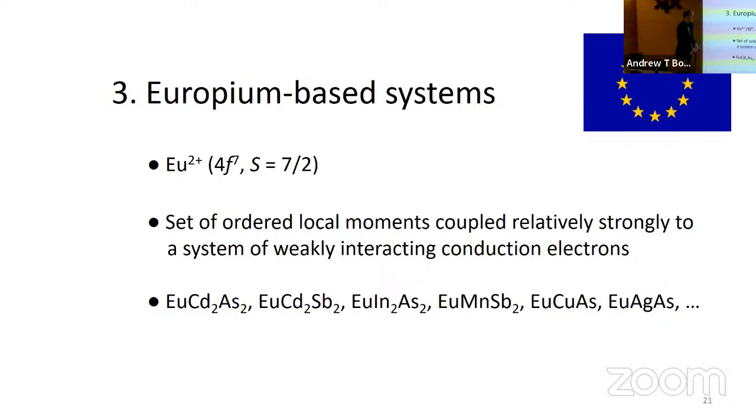A large family of europium compounds exists where you have divalent europium together with some other metal atoms. And divalent europium is quite nice because amongst the rare earths, usually you get a combination of orbital angular momentum and spin. But europium 2+ is just a pure spin, where the spins of all 7 electrons add up into a total spin of 7/2. So it's quite a simple system magnetically. You don't have to worry about orbital angular momentum.